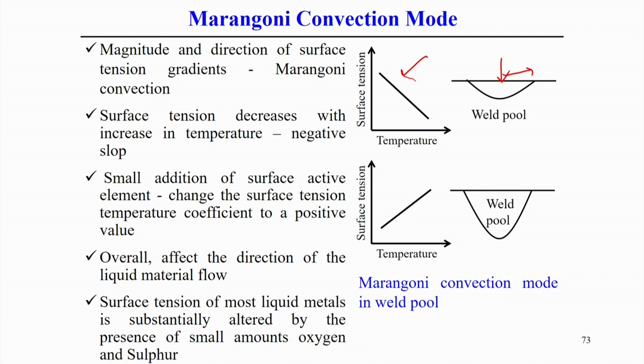In this case, the presence of this negative gradient creates the normal weld pool, normally having more width and less depth. Now, without any presence of surface active elements, this is the normal behavior of the material flow within the weld pool, represented by the negative slope of the surface tension with respect to temperature, and it creates the normal weld pool.